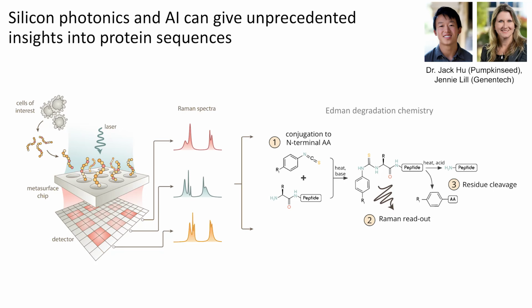So what we do is we take proteins, they're eluted off of cells, and then we put them onto our chip. They're oriented in such a way where all proteins have a carboxy-terminus, so we orient them by their C-terminus. And then we use an old-fashioned chemistry called Edman degradation, where you come in with this ring-type molecule, it binds to the N-terminus, and then if you do different pH cycles, it cleaves off one amino acid at a time.